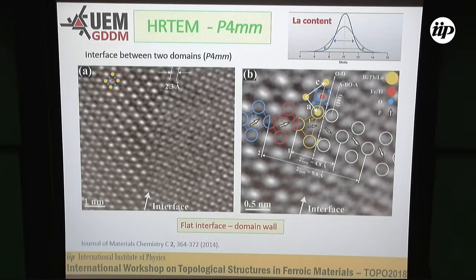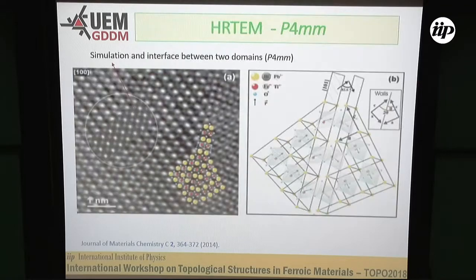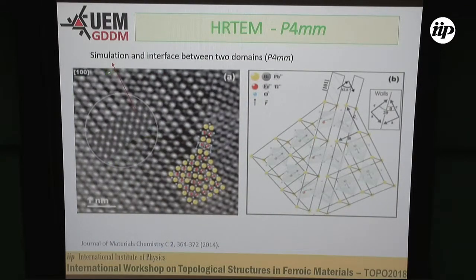It's a flat interface that you can now call a domain wall that can be arranged. If you change the domain landscape, this can change as well. Here we see the simulation, another region, the simulation of this interface. Here we reconstruct this interface for the tetragonal phase. And here we see the angle, two theta angle. This is the angle between two different domains in this only geometric reconstruction of the domain wall.